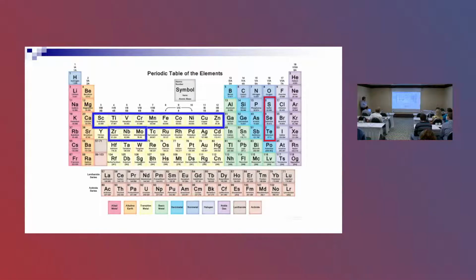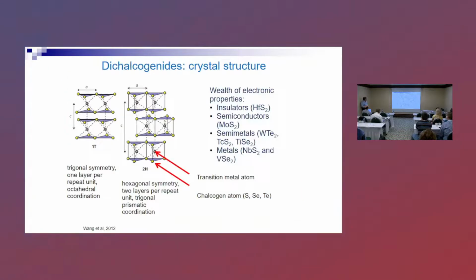Dichalcogenides are defined as having transition metals, usually 3d transition metals, and two chalcogen atoms, which are sulfur, selenium, and tellurium. There are also dichalcogenides with 5d elements, but I will speak only about one very small family, on titanium. The characteristic feature of dichalcogenides is that there are two different structures, and the same compound can be in two different structures. One has trigonal symmetry, presented here, where 1T means it repeats itself in one layer, and the other, in two layers, is the 2H structure, which has hexagonal symmetry.